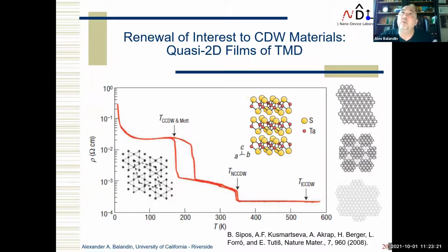1T means 1T polytype. So if you look at the resistivity of this material as a function of temperature, you see that it undergoes several transitions. At low temperature, around 180 Kelvin, there is a transition to the commensurate charge density wave. It's also accompanied by a more insulating transition, and you have a hysteresis. You go up and down in temperature. Then at 350 Kelvin, you have a transition from the nearly commensurate regime to the incommensurate regime, when you don't have translation symmetry. And then it becomes a normal metal at a temperature of about 550.